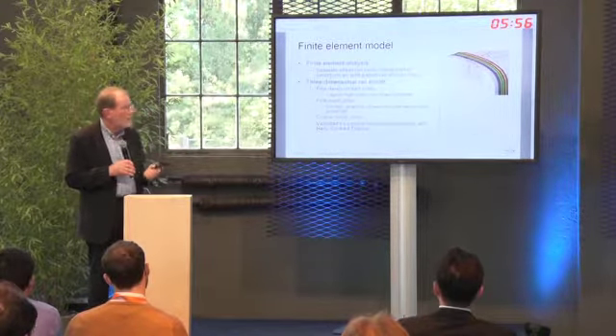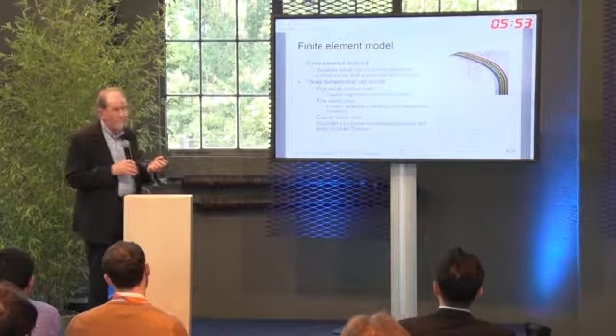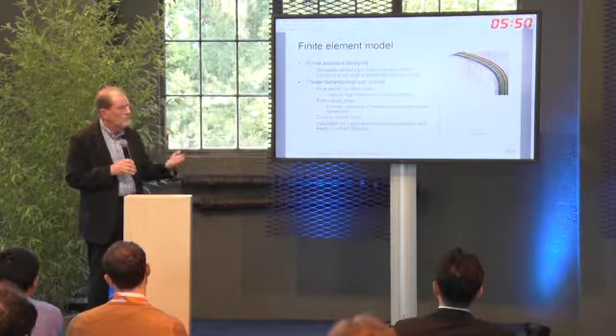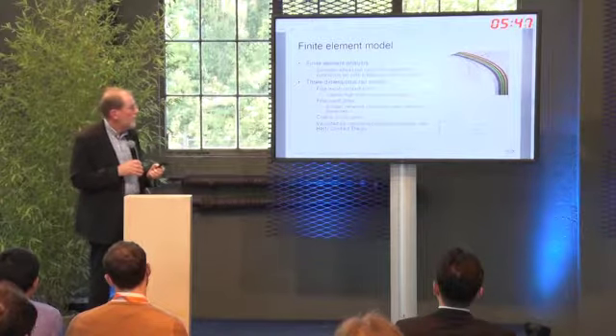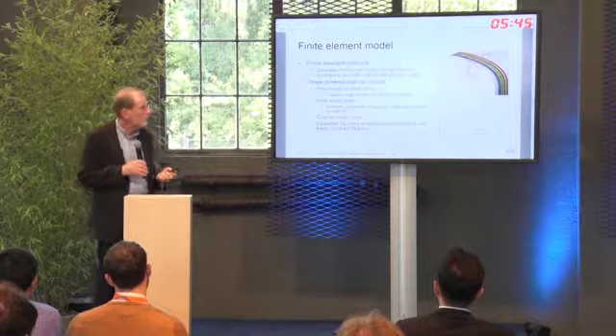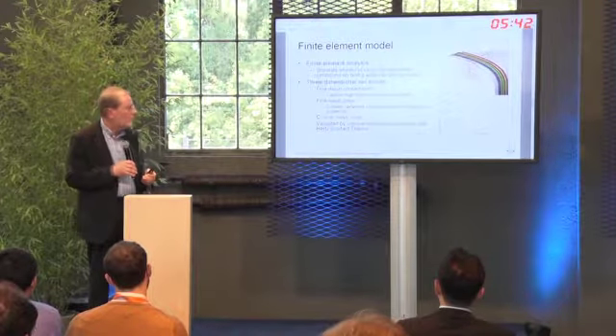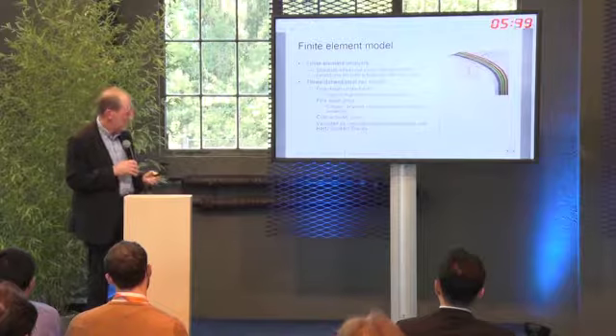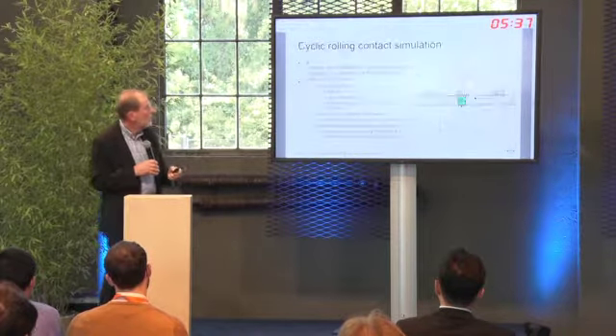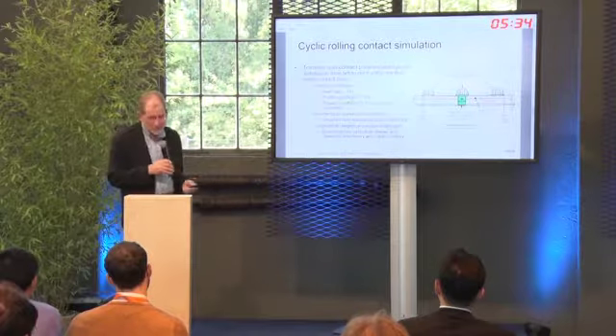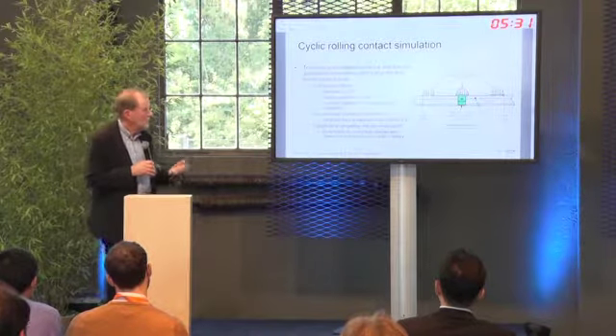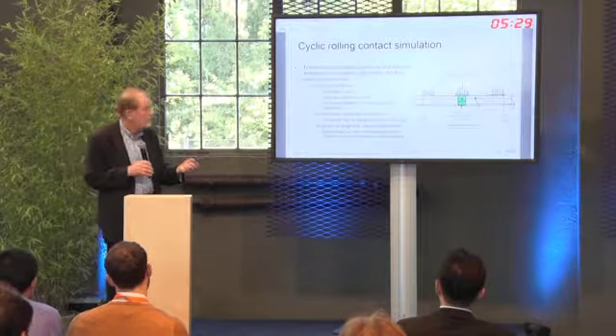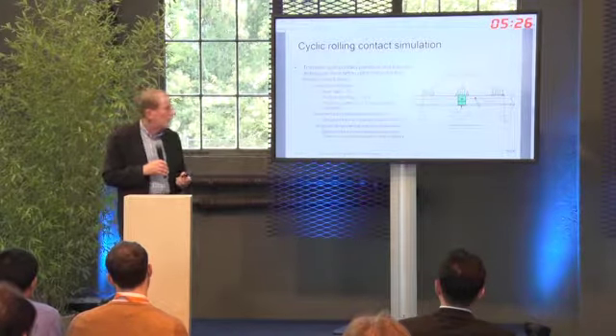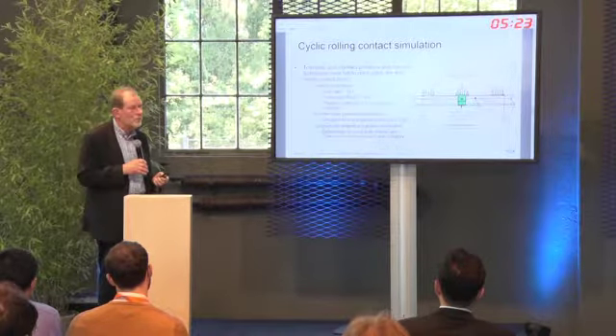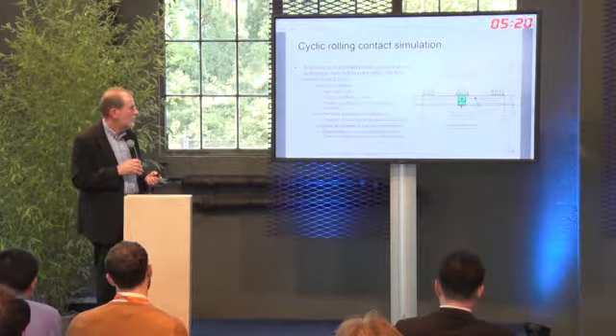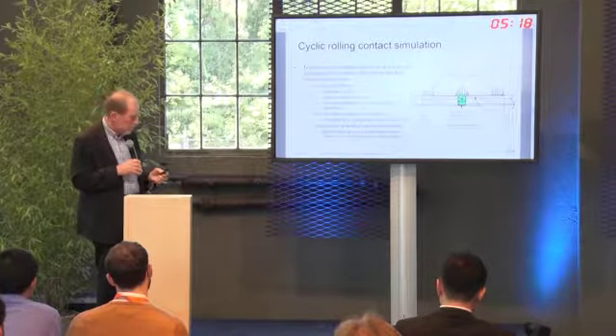This is just illustrating the modelling approach. Pretty straightforward, a fine mesh in the softened zone. One of the things we did initially was have both softened zones in the weld, so a full weld, but then to reduce the computational requirements, the later modelling was done with just one half of the weld and one softened zone. The loading conditions were 35 tonne. Typically these systems operate 35 to 40 tonne, friction coefficient of 0.4 and traction coefficient of 0.5, so fairly high slip or high traction type wheel rail contact conditions.